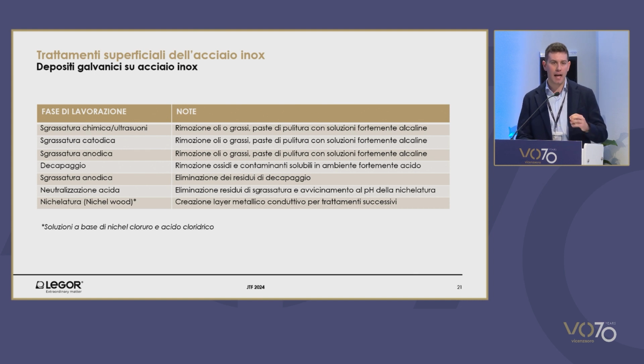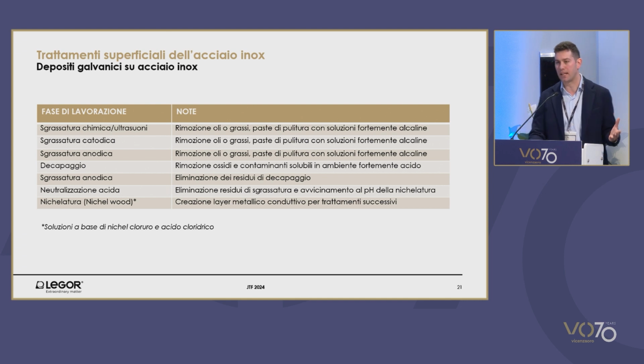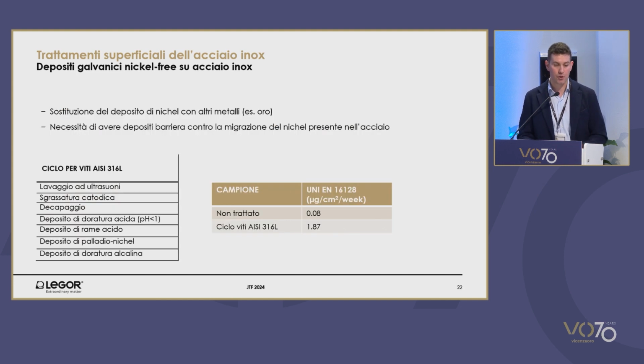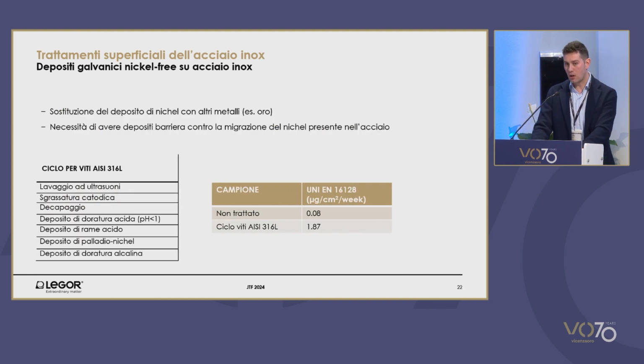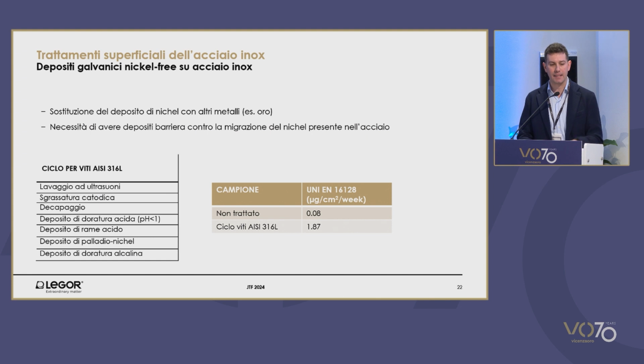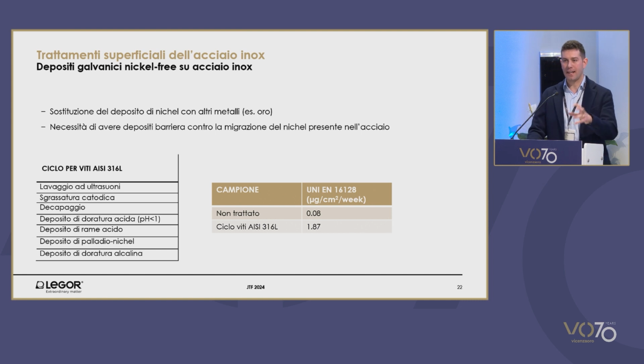And this is why, at the beginning, we tended not to resort to electrodeposition in the case of the fashion and jewelry industries, because nickel will be added, thus creating problems in terms of the release of nickel. Nickel-free cycles for stainless steel objects have been developed. You just have to remove the nickel deposition, usually replacing it with gold deposition.